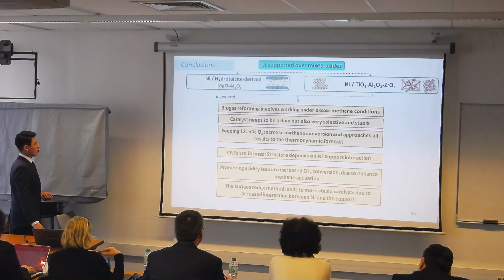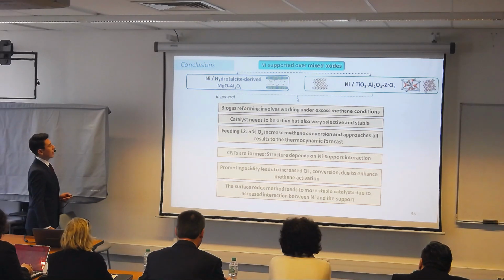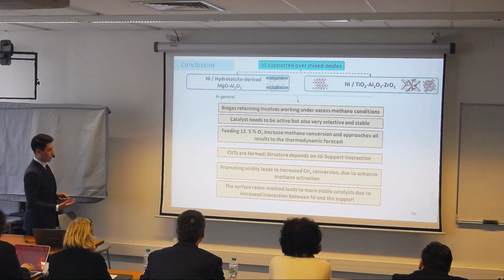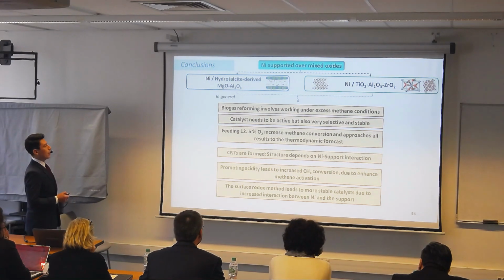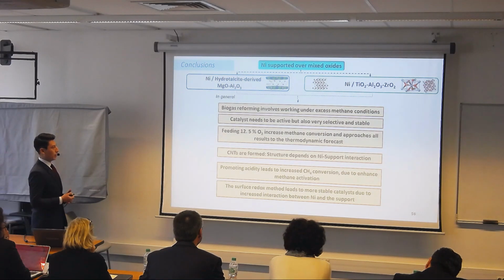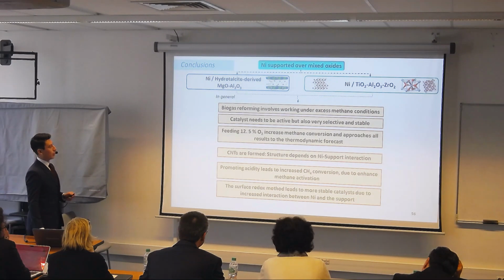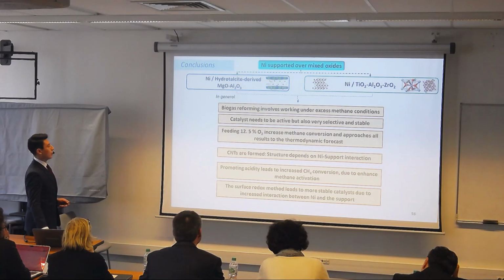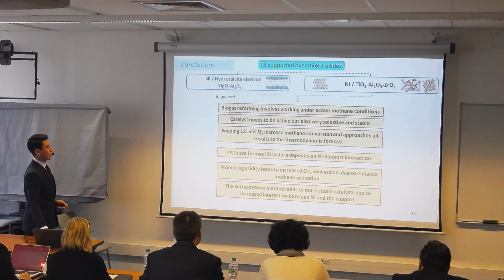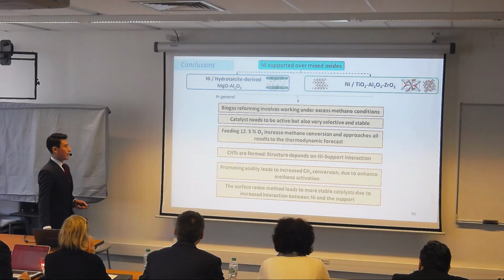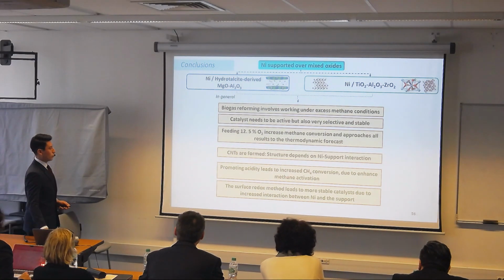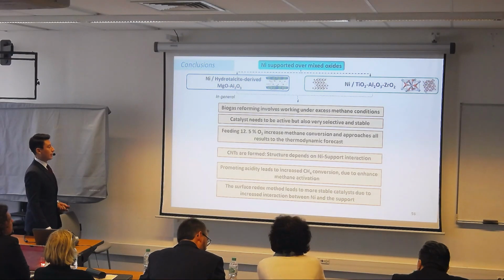In general conclusions, we tried reforming biogas, and this involves working under excess methane conditions. As we saw, we need a catalyst that has to be selective and stable in order to do this reforming. We also see the benefit of using oxygen in the feed mixture to increase the methane conversion and approach the values to the thermodynamic equilibrium. We always find carbon nanotubes after the test, and we promote acidity, leading to methane conversion. We find that this is a very important factor for methane activation. And finally, the surface redox method leads to more stable catalysts due to the increased interaction between these two phases, the metal and the support.